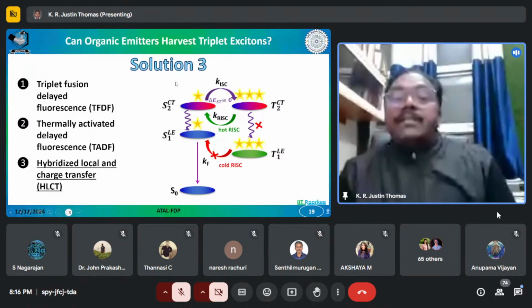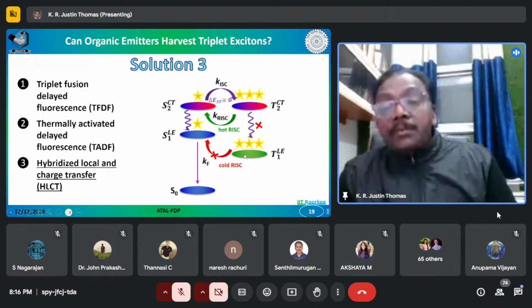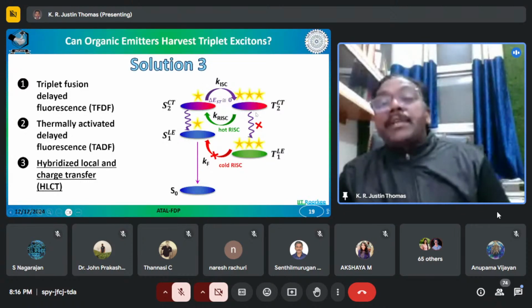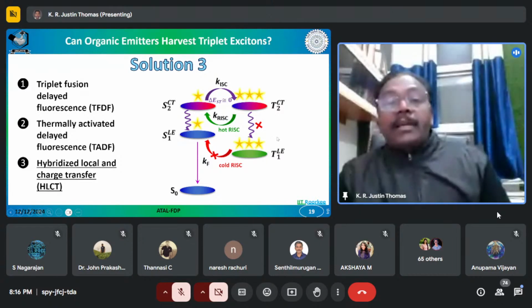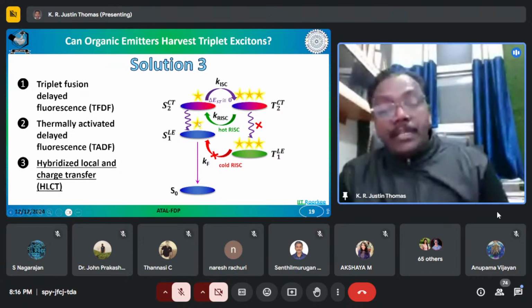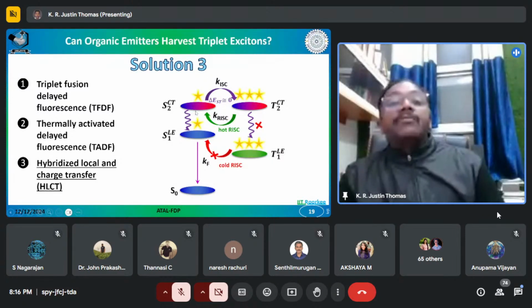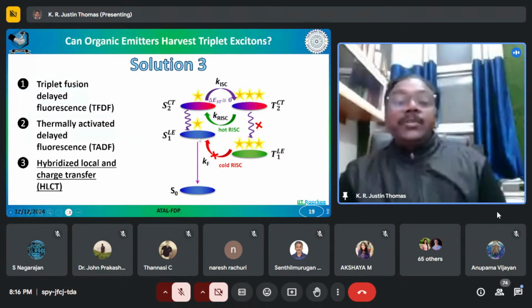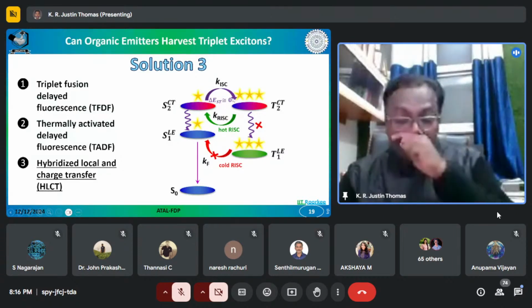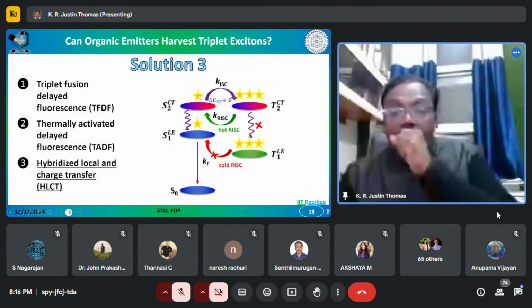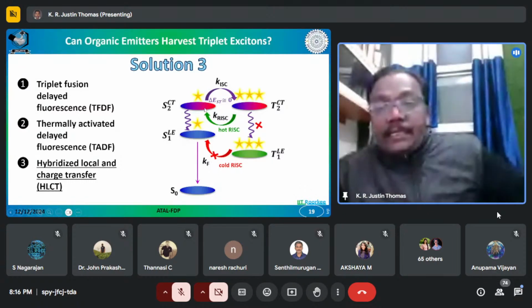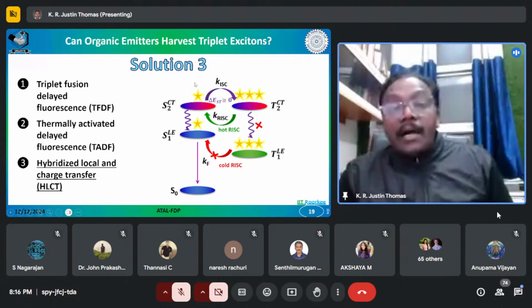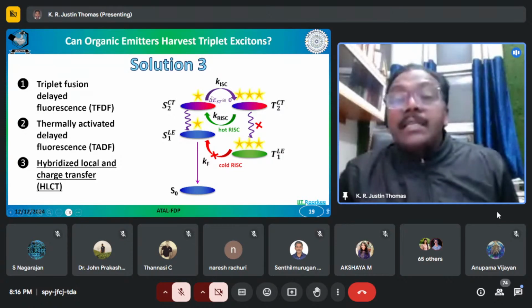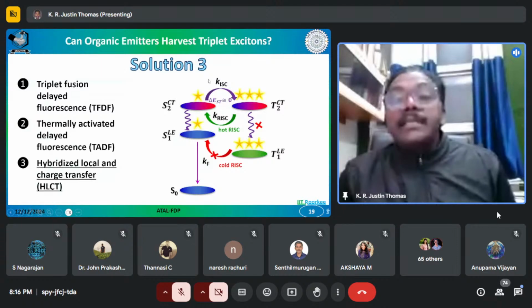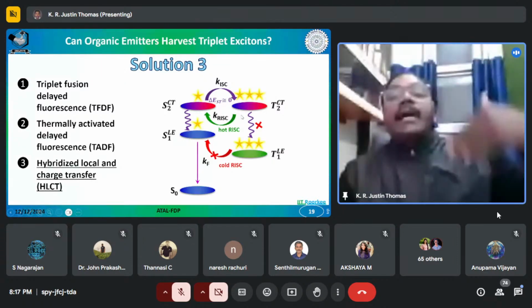So in such cases, even if the molecule goes from S2 to the T2 state, it cannot come to the T1 state because the gap between T2 and T1 is very large. However, the gap between S2 and S1 is very small, so it can have a facile interconversion. So in this kind of molecule, the triplet excited states can be converted to the singlet excited state by a hot RISC process. Why is it called a hot RISC process? Because the RISC is taking place at a hot level, a higher energy level.